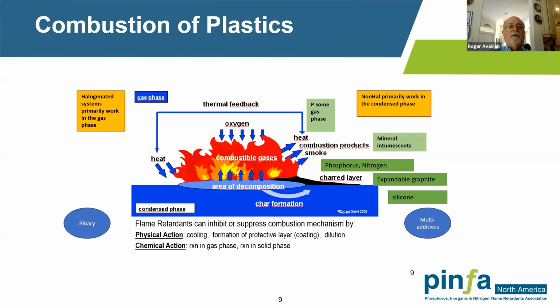On the other hand, the non-halogen flame retardants, typically the phosphorus-nitrogen flame retardants, as well as the inorganic hydrates, work in the so-called condensed phase. They work by a physical mechanism. So typically what occurs is you form a glassy char, or an intumescent or foamed-up char in the case of phosphorus and nitrogen flame retardants. And what that does is basically make it more difficult for the fire to access oxygen, and it also impedes the flow of the combustible gases out to where they can actually burn.